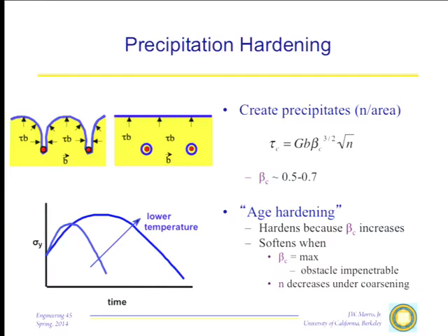You want to be low enough in temperature to get really good hardness, but you want to be high enough in temperature that you get it in reasonable time. You also have to be somewhat careful that the precipitate phase that you are using is stable enough that coarsening is negligible at the temperature in which you're going to use the material.